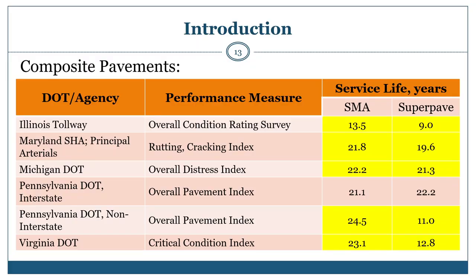Only one study, which was the Pennsylvania DOT on interstate pavements, reported a slightly longer service life for the Superpave dense graded mixes compared to SMA mixtures. However, it's an average of only slightly more than 1 year of service life for the Superpave mixes. Conversely, the 5 other agencies reported more than 6 additional years on the average of higher or longer service lives for SMA mixtures compared to their Superpave dense graded mixtures.